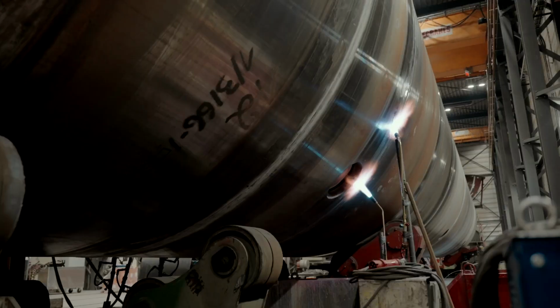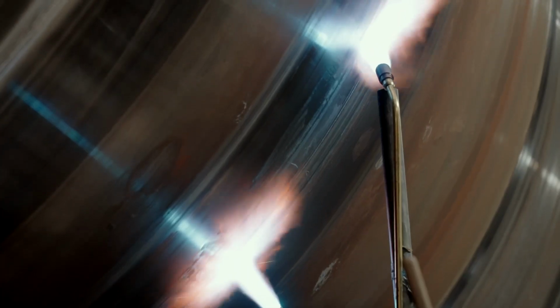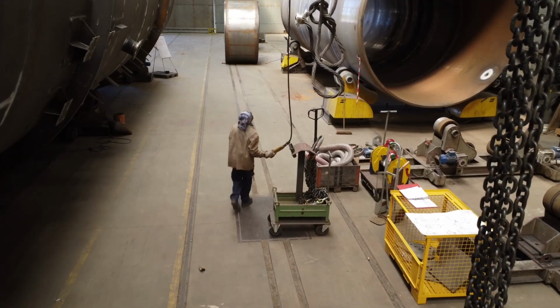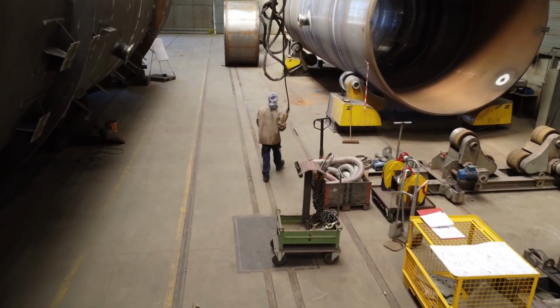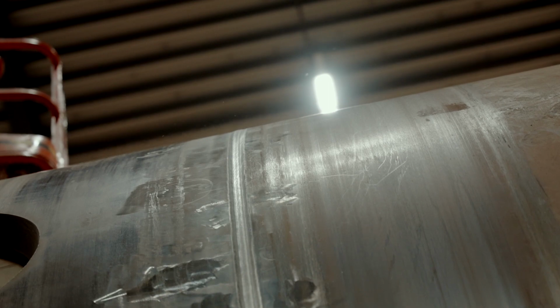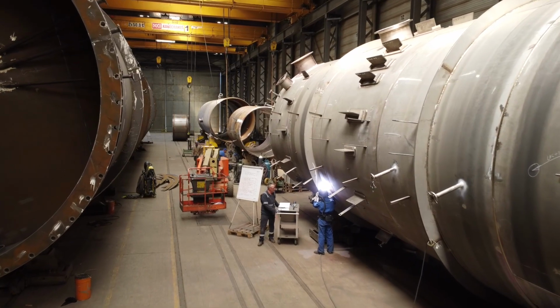Preheating this thickness to a temperature of 200 degrees Celsius and maintaining the interpass temperature below 305 degrees Celsius during welding is a challenge. The heat input needed to be controlled during the welding process to guarantee the impact values. After the welding, the material also needs to be hydrogen soaked at a temperature of 300 degrees Celsius for 1 hour. The complete reactor will be post-weld heat treated at a temperature of 619 degrees Celsius to regain the mechanical properties of the materials.